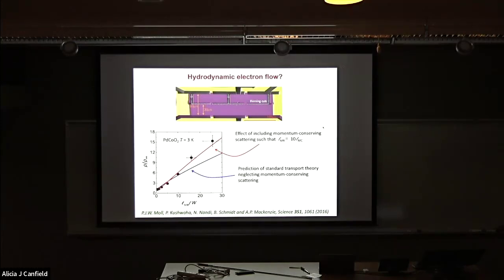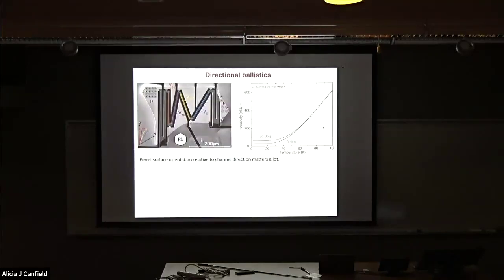Now, as it turns out, probably the conclusions we drew there were correct. But the thing that we missed was the importance of the hexagonal Fermi surface. So we did the analysis with the models we could write at the time, which had circular Fermi surfaces, and then subsequently discovered that that was not a smart thing to do, right? And the reason it's not a smart thing to do came from some work that Maya Bachmann did during her PhD, where she noticed in several mesoscopic experiments that the transport itself becomes strongly angle dependent when you get down to low temperatures and the mean free path becomes so long that it's much longer than the scale of your device. So here's one, you know, the games you can play are beautiful.